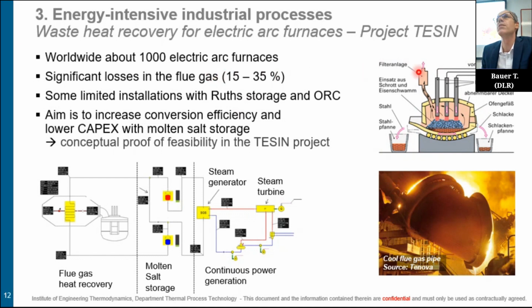There are some limited installations of Ruths storage systems. So what they do, you can see a picture at the bottom, is install a heat exchanger in the flue gas stream here. This is a heat exchanger with direct steam generation. And then they inject it into a Ruths storage system, and they couple this with an ORC process. But this process is not very efficient. It's expensive, the ORC. The Ruths storage has a decline, so you don't have a constant temperature outlet of the Ruths storage. So this is not an ideal solution.